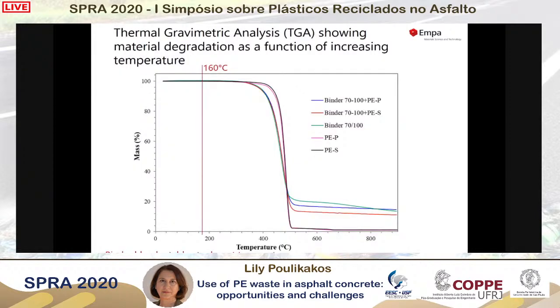It is also important to know the characteristics of our material and the blends. How do they react when it comes to temperature? Here are the results of the thermogravimetric analysis. On the vertical axis, you see the percent mass, and on the horizontal axis, the temperature. As the temperature increases, there is degradation of the material, a mass loss. However, at our working temperature around 160, where I put this vertical red line, the mass is not changing. So our material is very stable within the working temperatures of asphalt concrete.